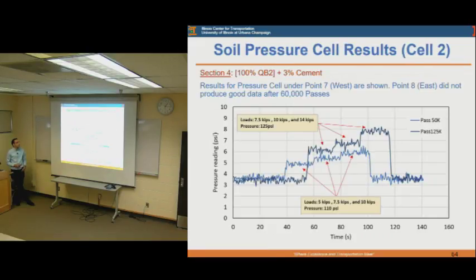I also mentioned that we had some soil pressure cells embedded on top of the subgrade in the different test sections, and I'm here showing some results for static loading of the pressure cells. So we were moving the tire on top of the pressure cell and then recording the pressure on top of the subgrade. Here is shown for cell 2 for the 2 different pressures.